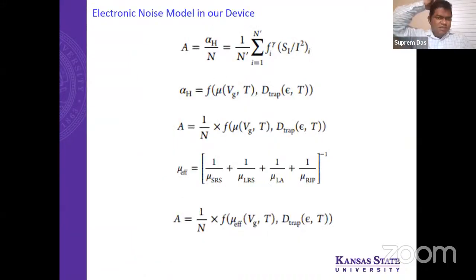Now, to understand how we can have a better knowledge about the origin of noise, we have a model. We derived a model. Basically, your noise amplitude is some factor, say alpha, which is a characteristic constant, divided by N. N is the number of carriers in the channel, and you can actually sum over all the frequencies, and that is basically frequency times your noise amplitude divided by the drain current squared. So basically your alpha_H over N is equal to f, which is frequency, times S_I over I_D squared.